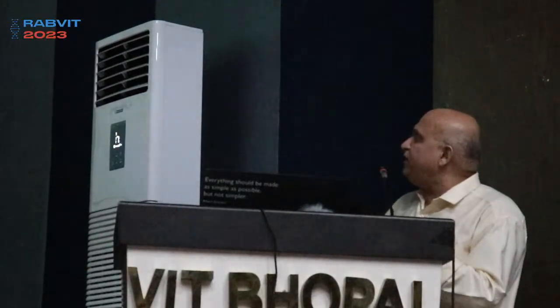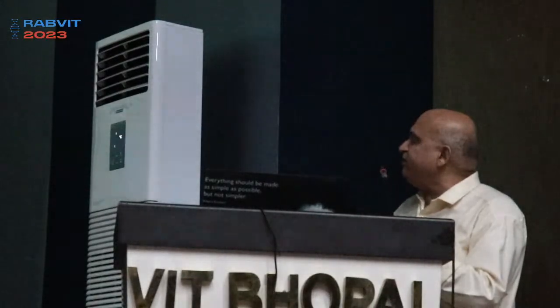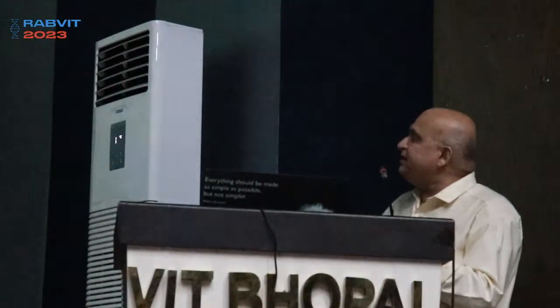Now this is very important. This is actually also controlling the hydrodynamic size because the charge is changing from the negative to the positive one. So you can see the hydrodynamic size is actually reduced at this point. And that may be the reason why this is more dispersed. So there is some important thing which we can find in this study about this sample. So the pH has increased the positiveness of the surface charge. So what is exactly causing this?